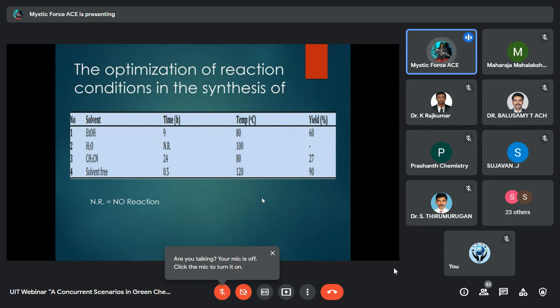So this whole reaction, as you can see here, we have done in solvent free condition, and here you can see the time decreased. It was half an hour. The temperature we have to increase up to 120 degree, and the yield increased to 90. So in few reactions we can't use water.